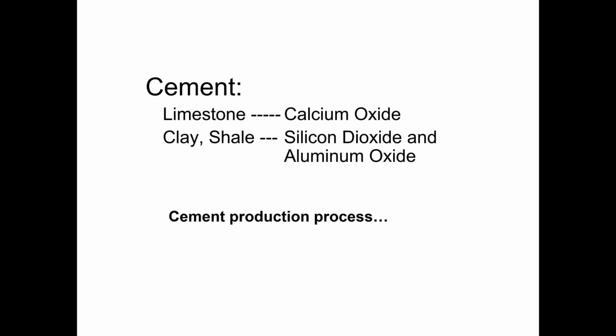So the components for cement are primarily calcium oxide, silicon dioxide, and aluminum oxide. The sources of those oxides can vary, but the most common sources are limestone for the calcium oxide, and then clay or shale for the silicon dioxide and aluminum oxide. So those are the three primary oxides, and we're going to take these naturally occurring materials, limestone, clay, and shale, and some other materials as well, and blend them together in the cement production process, so that we go from these raw materials on one end of the process to this fine powder that we know as Portland cement at the other end of the process.